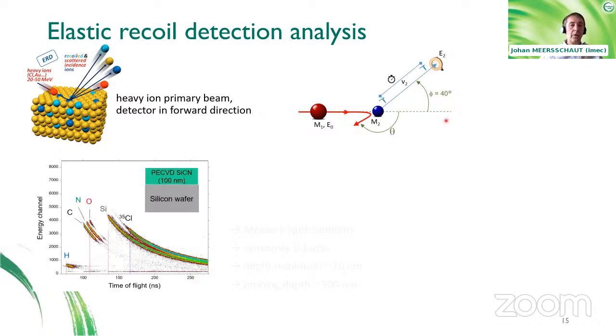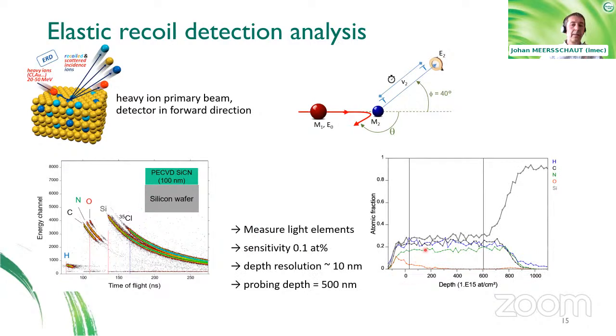And for that, to overcome that limitation, we have a two-dimensional data acquisition which records both the velocity and the energy of the ions, from which you can readily recognize the quadratic behavior which is related to the mass of the emerging ions, of the recoiling ions. At the same time, the energy dependence gives you a measure for the depth at which this scattering occurs. But for the rest, all the kinematics are very similar to what we have seen in, for example, Rutherford backscattering spectrometry. By analyzing these data, we can reconstruct the depth profile, which is plotted here.